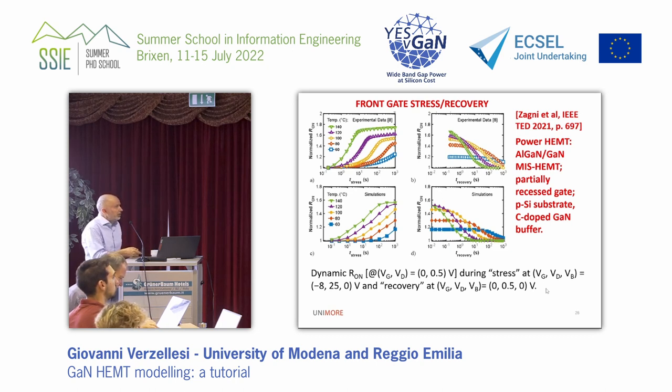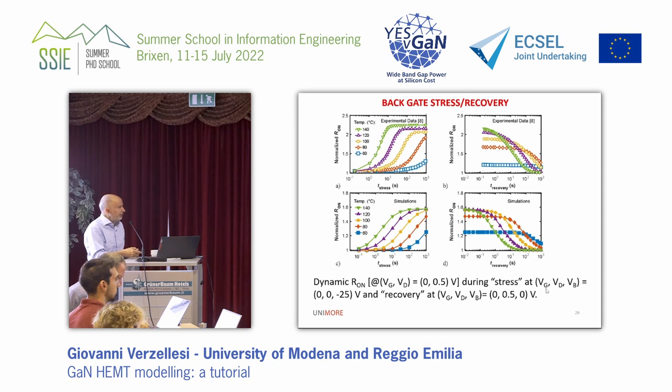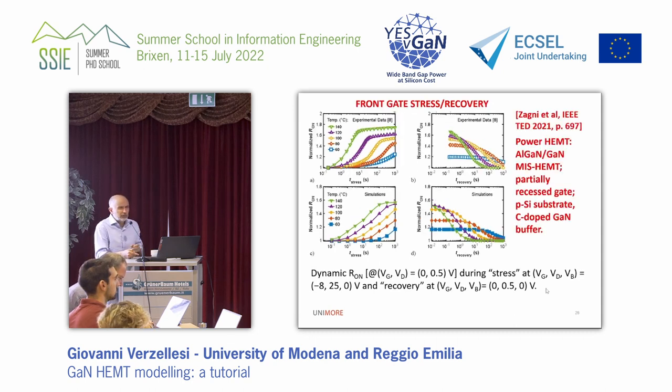And these are the simulation results to compare with the experimental ones. Okay, experiments were twofold. These are experiments and corresponding simulations obtained by means of front gate stress and recovery. And these are the stress conditions, -8 V of VGS, 25 V of VDS, and 0 V applied to the bulk, to the substrate, and recovery, I mean, on-state condition, just to measure at different stress times. And then, same conditions to monitor the recovery transient.